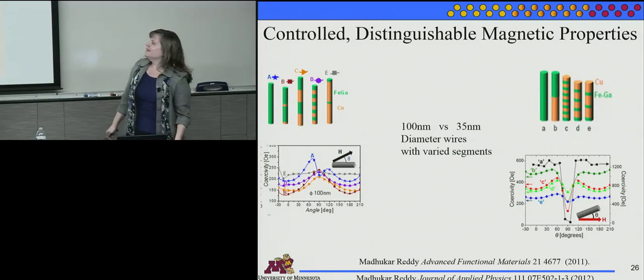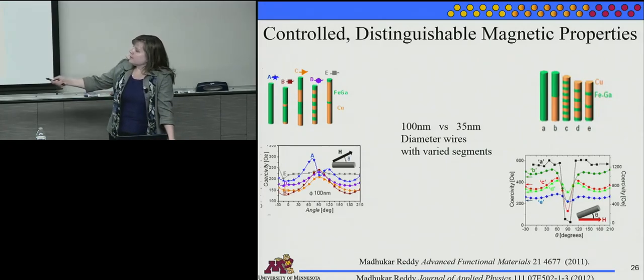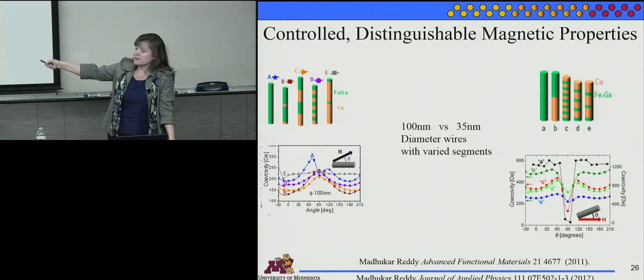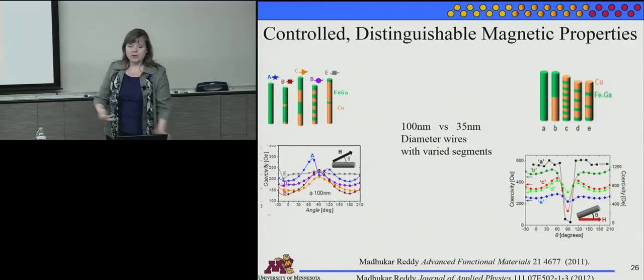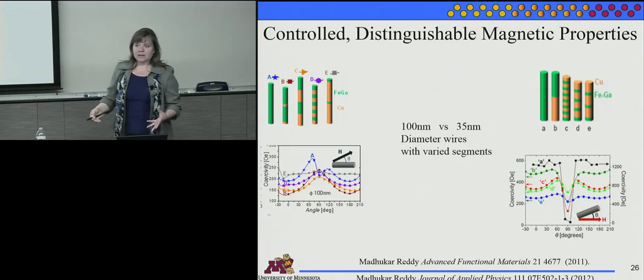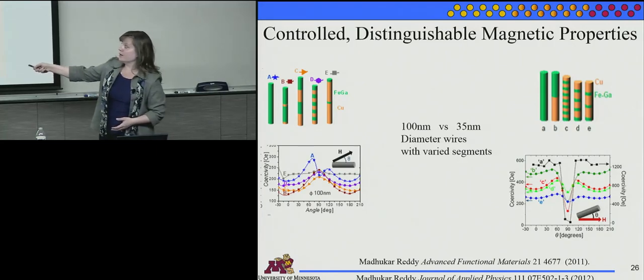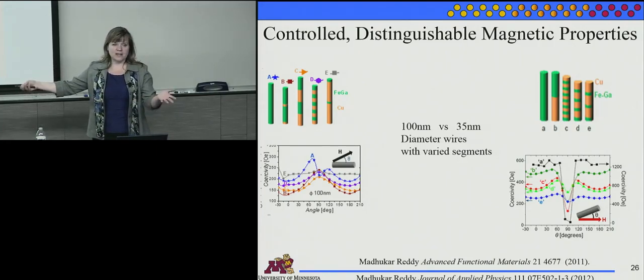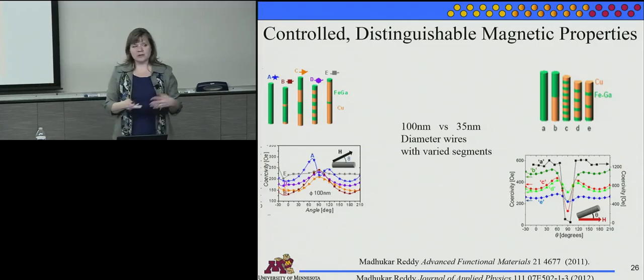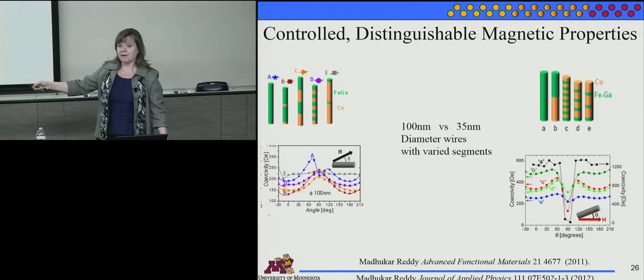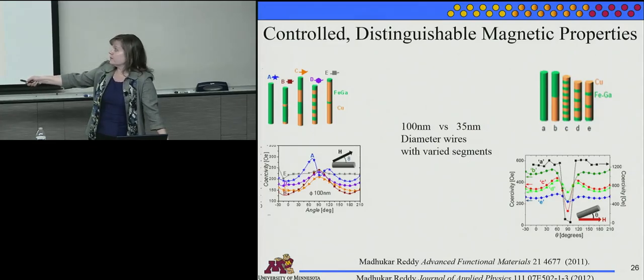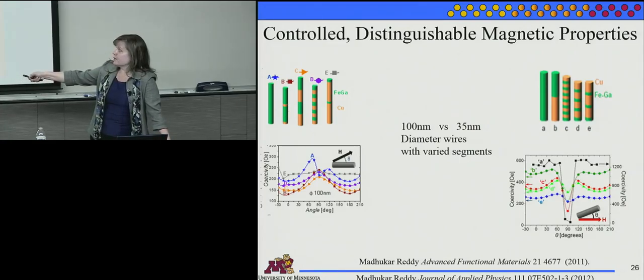Pretty good. And why does it matter? Well, if I want to claim that I have different magnetic properties with this sample versus this sample, then I need to have grown the entire sample that way. Because otherwise I'm measuring an agglomerate of all of these in one hysteresis loop, and I can't really tell. Every single sample looks sort of the same, and that looks like a washed out version of all of these together. But once you control the growth, you can see that A here is very different from E.